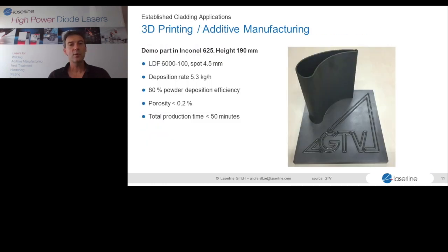The last, also very well-established process is 3D printing, additive manufacturing, maybe the most recent one of the established applications. This shows an example of a part that is something like 20 centimeters high and was built up in less than 50 minutes. There's a very high powder deposition efficiency, so more than 80% of the powder is in the final part. So this is a demo part in the shape of a blade, also with very low porosity and built up really from the simple plate you can see from the beginning.